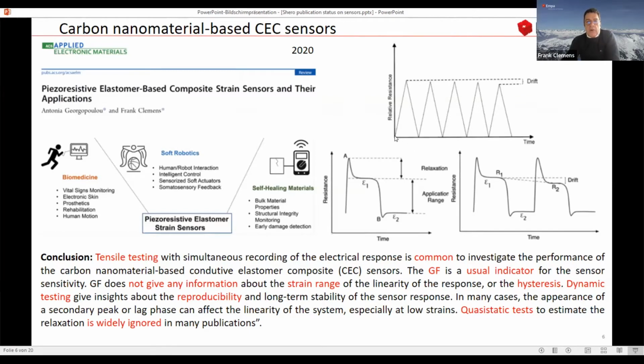That means it tells you how much the resistance changes from the initial resistance, where you had no strain on it, up to a certain strain which you apply to the sensor. And then typically what you can see in the literature is that people have a kind of drift, so that the first, second, third, fourth, fifth, and so on cycle do not always achieve the same resistance at the same strain. However, if we want to have a very good sensor, you can imagine that this drift must be very small or even negligible. And another possibility to measure sensor properties, and to see if you have a good sensor or a bad sensor,